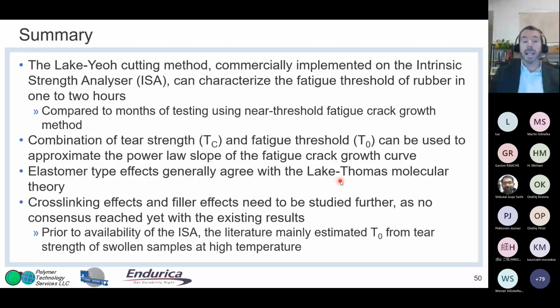Lake-Thomas gave us a nice molecular view of fatigue crack growth at the fatigue threshold limit, and it generally predicts elastomer type effects. However, cross-linking effects and filler effects need to be studied further, with no real consensus yet. And all of the literature prior to the intrinsic strength analyzer was mainly estimated from tear strength of swollen samples. And that may be one of the reasons why we have some disagreement among the data results.